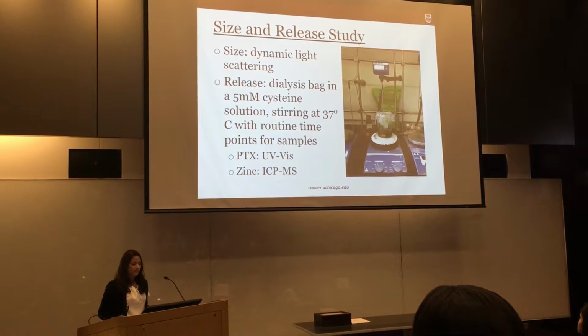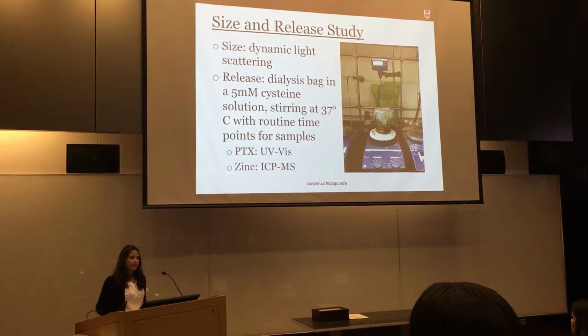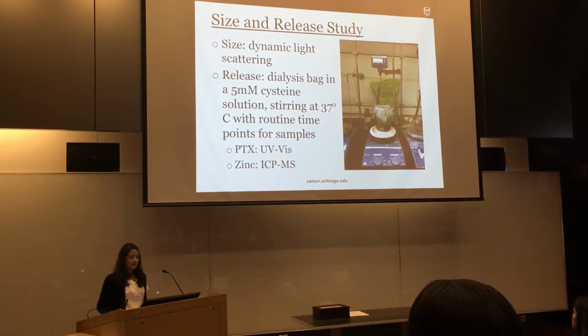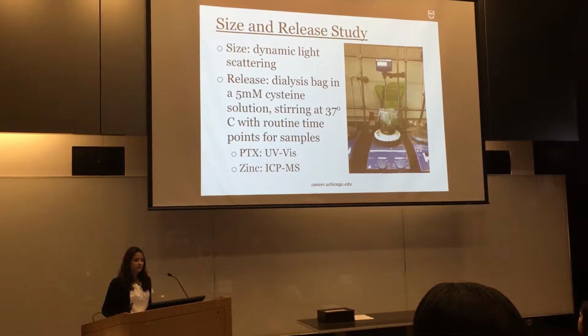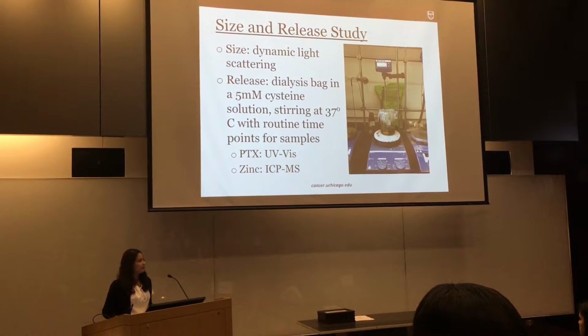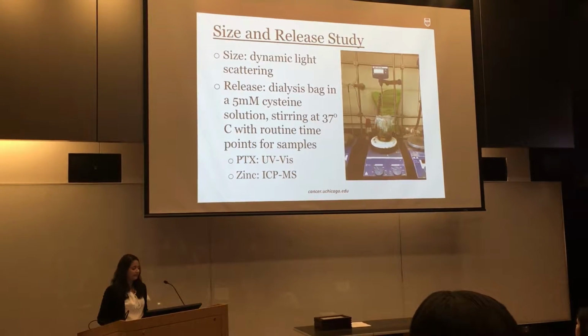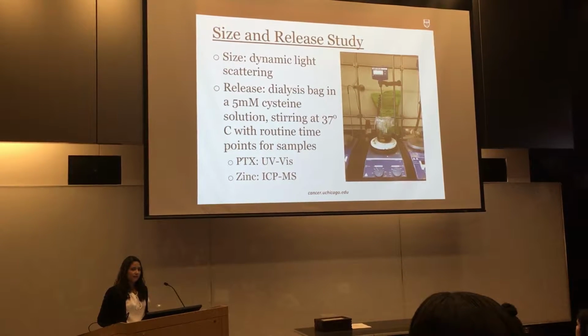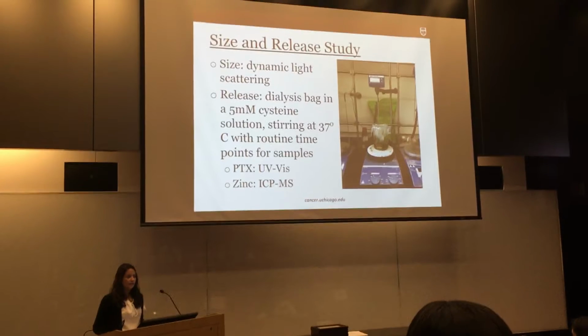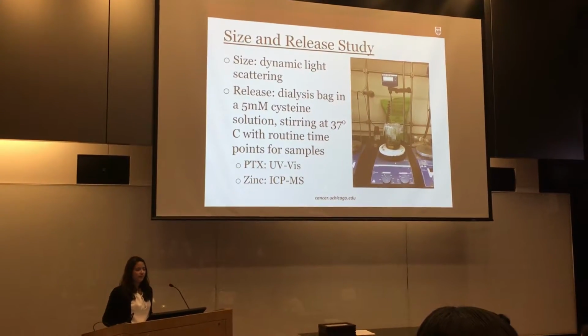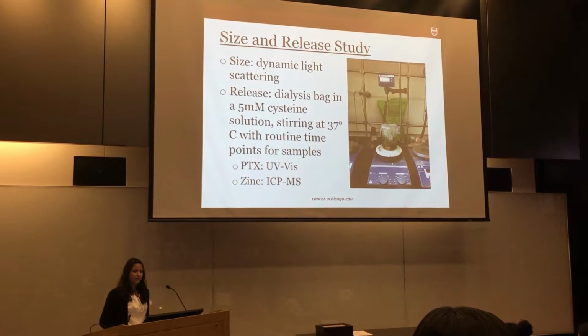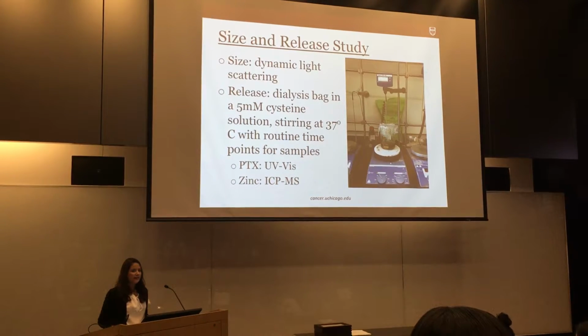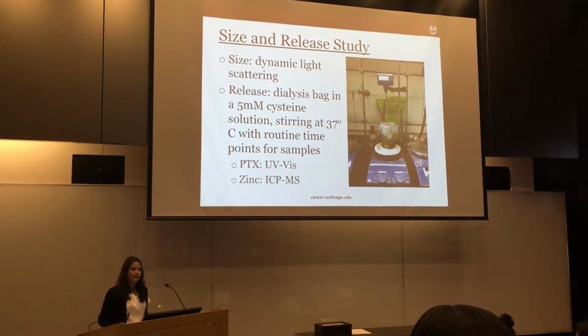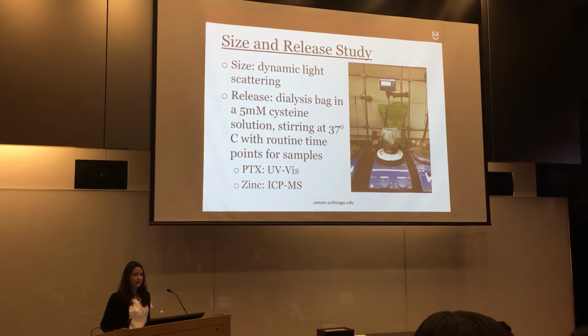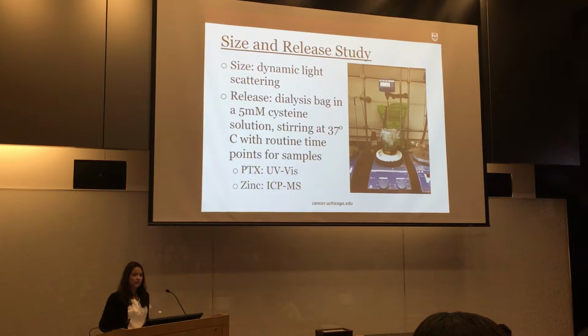To measure the release of particles, I filled a dialysis bag with 6 milliliters of particle suspension and put that in a 5 millimolar cysteine solution, which was stirring at 37 degrees Celsius, as you can see in this setup displayed above. At routine time points, 1 milliliter samples were removed from the cysteine solution and replaced with 1 milliliter of fresh cysteine solution. These samples were then later analyzed for Paclitaxel and for zinc concentration. To measure Paclitaxel concentration, standards of known Paclitaxel concentration were made in 30-70 methanol PBS and their absorbance at the peak wavelength was measured using UV-vis spectroscopy.